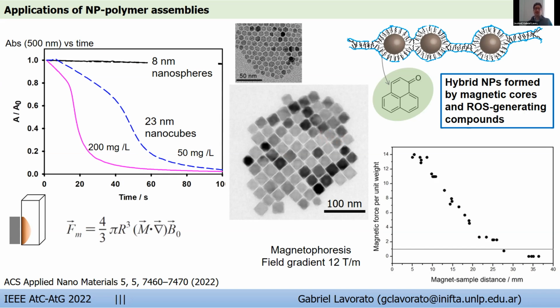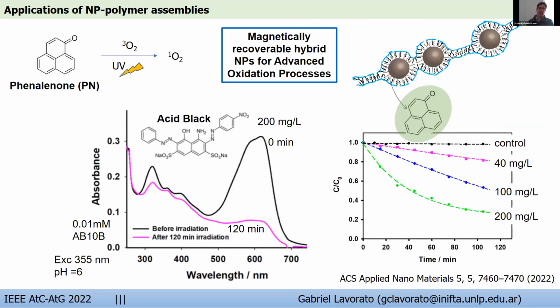So we characterized the magnetophoretic response to show that the particles can be separated from the solution at different distances from the magnet. And to check our proof of concept, and to demonstrate the utility of this system, we showed that the hybrid system can be used to photodegrade acid black, which is an organic dye that is a common contaminant of textile industries, indicating that this approach may be an alternative to other advanced oxidation processes that require, for example, much lower pH values.